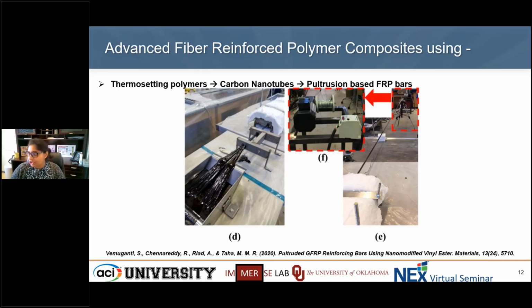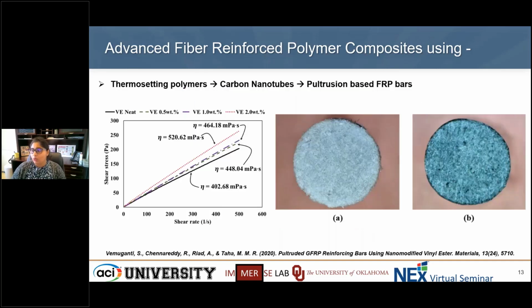This is a small laboratory scale test setup. But the resulting bars were tested for different kinds of mechanical properties. For the resin itself, we wanted to make sure that it's very suitable for pultrusion, and for that the flowability should not be affected that much. When we looked at shear stress versus shear rate, so rheological measurements, we saw that the shear stress was not highly affected with respect to shear rate. So the flow of the resin itself is not highly affected by the addition of these fillers.